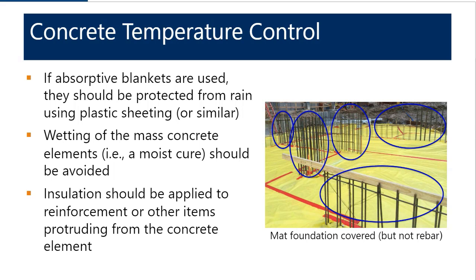If you have reinforcement that's protruding from the surface of a mass element, that reinforcement should also be insulated as well. And so you can see an example here on the right where they did a pretty decent job of covering the surface of the concrete, but did not insulate the reinforcement.